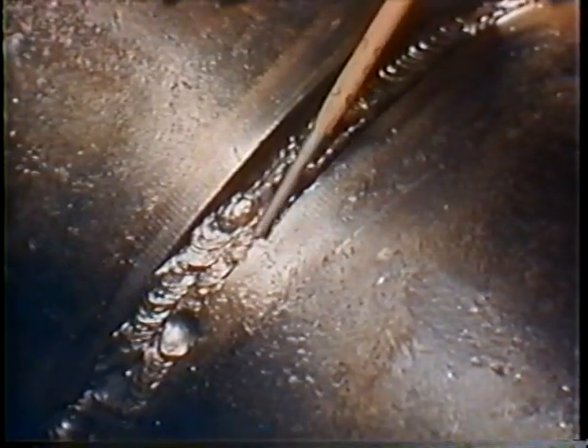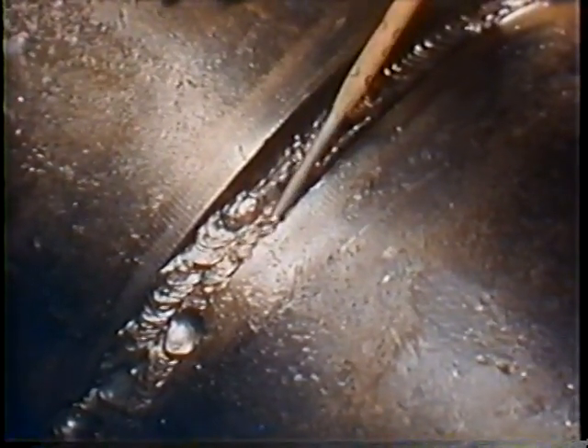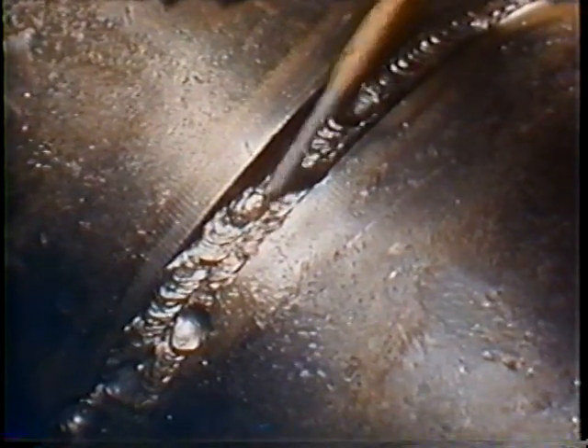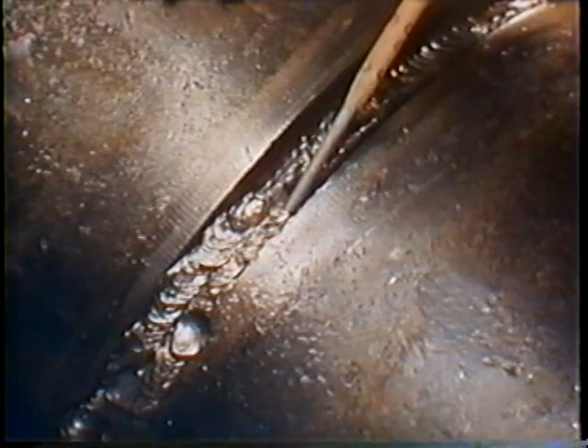The third bead was placed here, as you see. Tie it in. You notice we just about filled up to the top of the groove with this third pass. Again, making sure we fuse in at the sidewall of the pipe and halfway into, or to about the center of this second bead. The next weld, of course, then is placed here. Again, making sure we tie into this wall of the pipe.